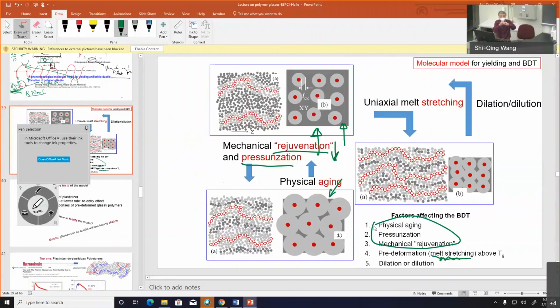So that I can improve that pull-out force and therefore accomplish the job of activation before chain pull-out takes place. So that's my interpretation. Very hand-waving, but totally satisfying to me, without getting into any complications, to appreciate the effect of pressurization, which makes polystyrene at room temperature ductile to hydrostatic pressurization.